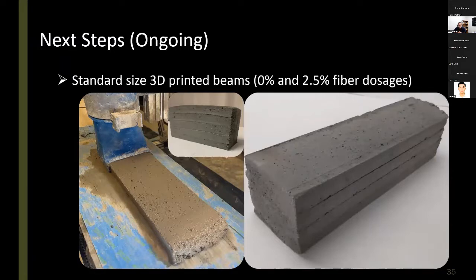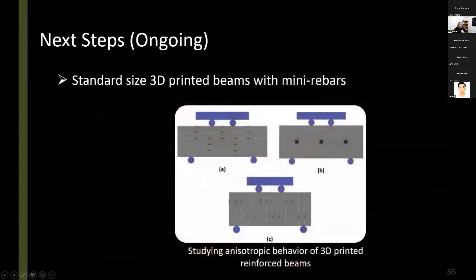These are 100 millimeter by 100 millimeter by 350 millimeter samples, both with 0% and 2.5% steel fiber that we have been able to print in the lab. And we're gonna basically study the anisotropic behavior of these 3D printed samples in different directions, loading directions.